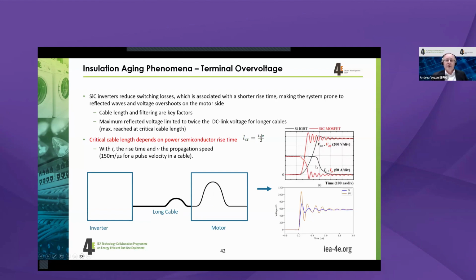But as you can see here, naturally the switching speed of silicon carbide is again much faster than with the silicon ones. So all the technology advancements which have been done on the insulation properties for IGBT-based inverters have now to be re-questioned, to see if this is also possible for the switching speed of silicon carbide. The switching speed will lead to over voltages, and this over voltage is heavily dependent on cable lengths and filtering at the output of the inverter. So we could have some filters directly at the output of the inverter and therefore decrease the impact, or without filter, the cable length is basically the most important factor.